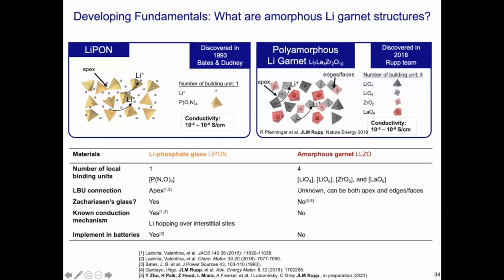So we were the finders of these and described the first polyamorphous lithium garnet structures where you can have this chemistry, but you can have various amorphous states. Now, what's very different to LiPON is that LiPON is a classic Zachariasen glass. So you have all these different tetrahedra, that's the little triangles you see here, of phosphorus, oxygen, nitrogen, and some can form dimers. So you would just click here with another triangle, and then you can have the lithium actually migrate in this material in a random walk.